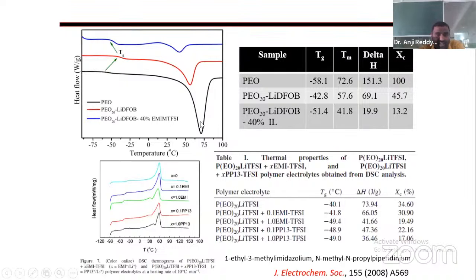This is more crystallinity. If you add the lithium salt, the crystalline nature decreases. If you add ionic liquid, the crystalline nature decreases more. If you compare with the pure PEO, the crystalline nature we can take as 100%. The crystallinity is reduced to 45.7% after adding lithium salt, and after adding ionic liquid 40%, that is decreased to 13.2%. That means if we increase the amorphous nature, the conductivity will increase, no doubt. That I am comparing with the same, whatever conductivity I compare. Here also the crystallinity is reduced up to 17.06 is minimum, right?